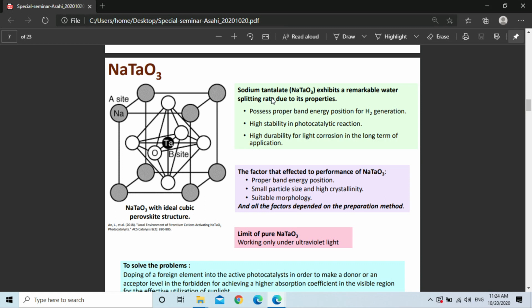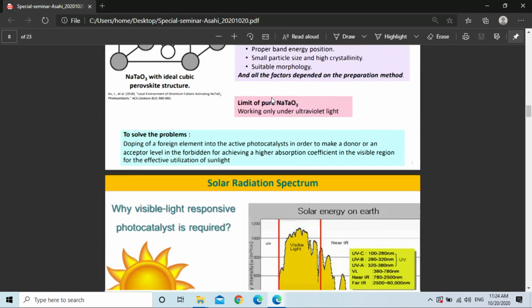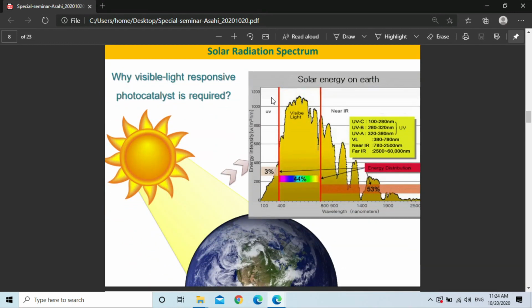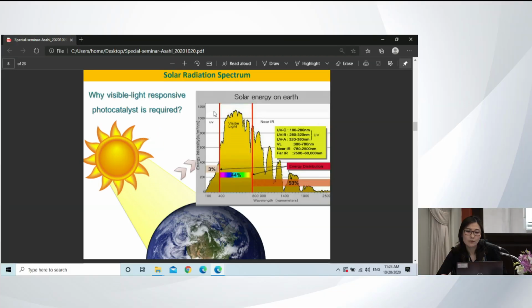Anyhow, the limitation of this material is that it has a wide band gap energy of about 4 electron volts, so it can be activated only under UV light. The challenge is how to improve this material so it can be activated under visible light, because the spectrum of sunlight or solar energy that comes to the earth contains more than 44% visible light, while UV light is a very small amount, less than 5%. So if we can make this material active under visible light, it will effectively utilize sunlight or renewable energy.